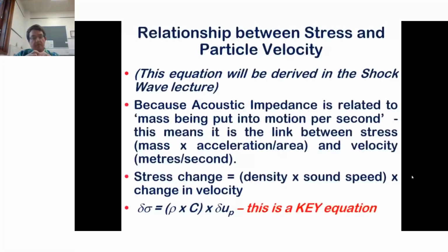And the relationship between stress and particle velocity in the system, which can be derived in a shockwave lecture, which I can't give. The defining equation here is change in stress equals density times sound speed times change in particle velocity. Particle velocity changes at the interface, changes due to transmission of energy through the material. So the change in stress equals density times sound speed times change in particle velocity in the elastic regime.